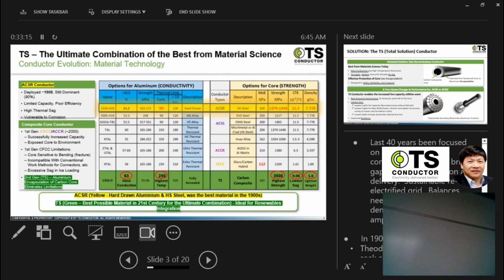And this is how ACSS is developed, and that's also where ACSS is typically used, which is reconductoring, to get that additional capacity. However, when you use ACSS, you do have to deal with the compromised thermal sagging in particular. Why? Because we're still featuring steel in the strength member, and the steel material is still heavy, and they have very high thermal expansion. So what does thermal expansion have to do with the conductor? Well, when the lines run hot, the stretching of the steel makes the conductor longer, and that results in sagging. And that sag is actually substantially more than the baseline conductor, which is typically ACSR.